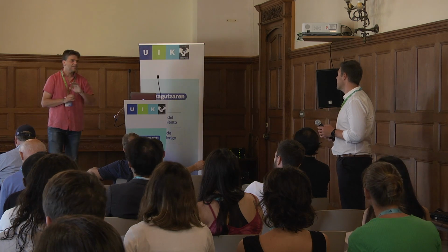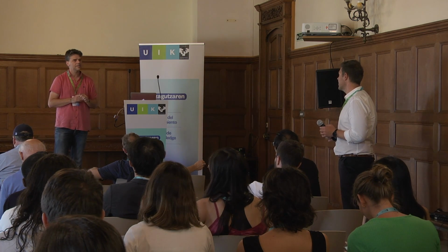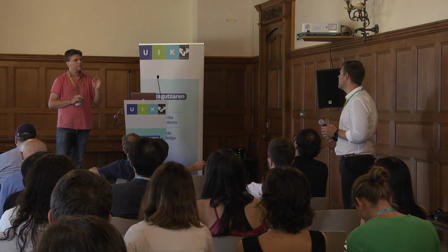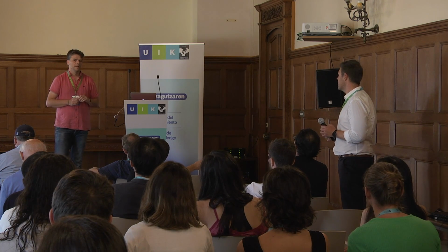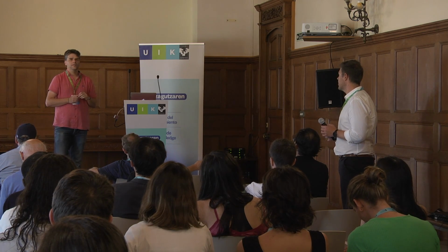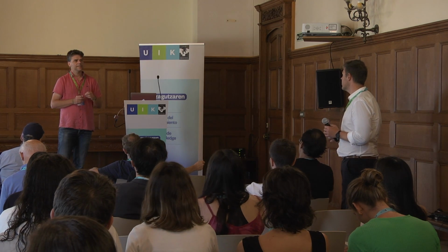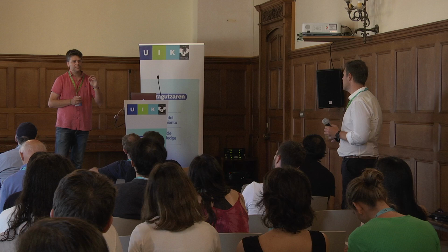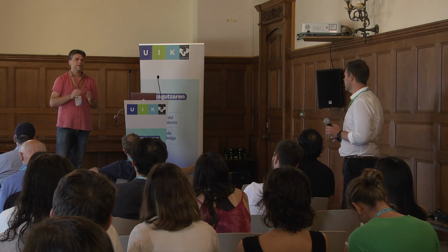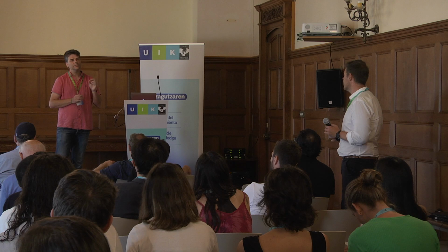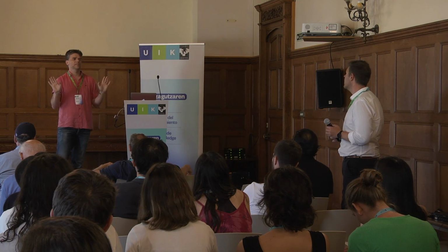If I have an image that has a background, I try to reduce the tapping amplitude, the power, or whatever, to be free of background. One hint that I use: when I have a clear near field, I try to get the maximum of the near field, increasing the power and other parameters, until you get some constant value in the phase. The phase is completely noisy if you don't have background.